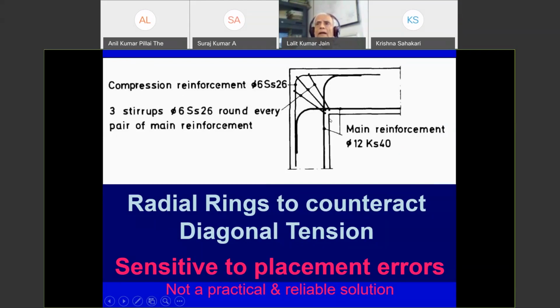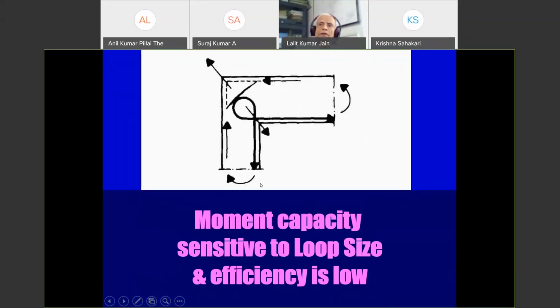But it's very difficult to provide, and people did research earlier. On this type of joint, research was done even before World War II, and it continued in the 70s, and no solution was found. This was known in the 50s also, '48, '45, '50. It was known that we should have diagonal steel, but they found that the effectiveness is very low, and this is very prone to placing errors of the steel, so it was not practical. One of the best things known before the 70s was that we provide the steel in a loop. We loop the steel and continue. That was the best type of detailing known at that time.